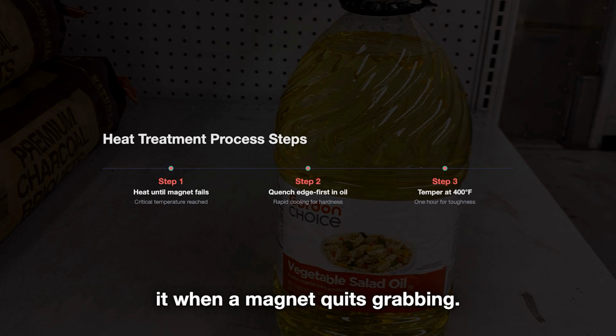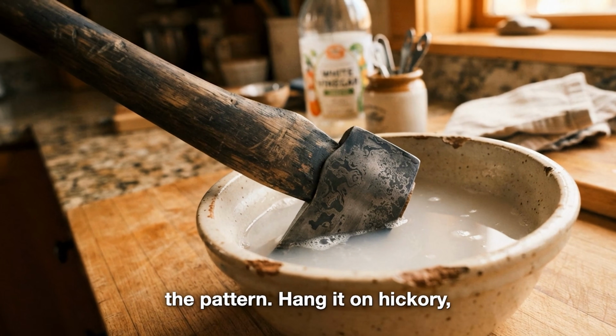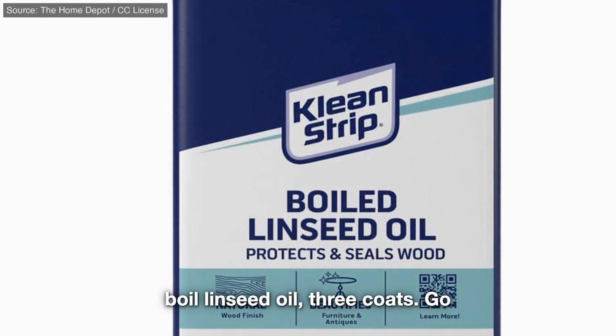Harden it when a magnet quits grabbing. Quench in oil edge first. Temper at 400 degrees for 1 hour. 2 hours in warm vinegar for the pattern. Hang it on hickory, boiled linseed oil, 3 coats.